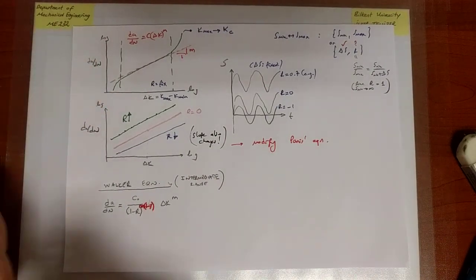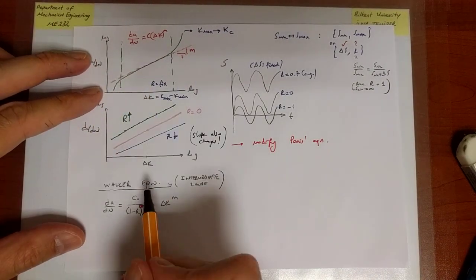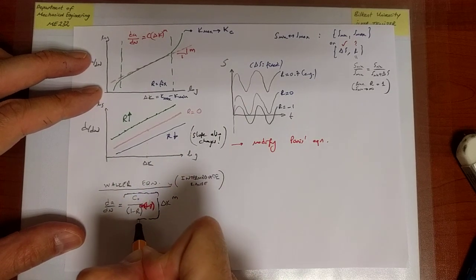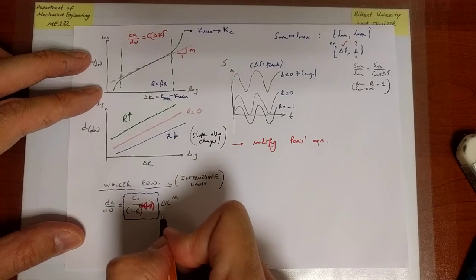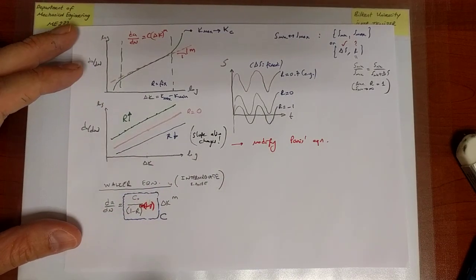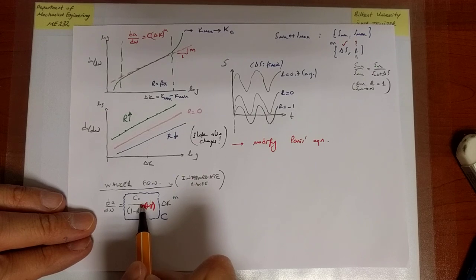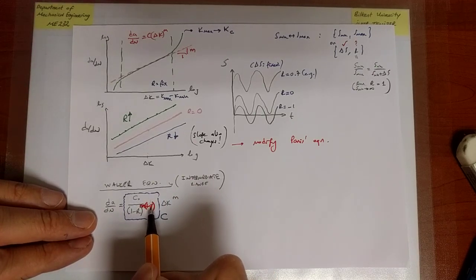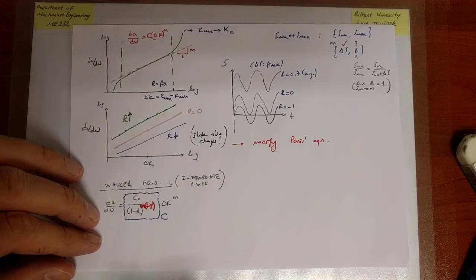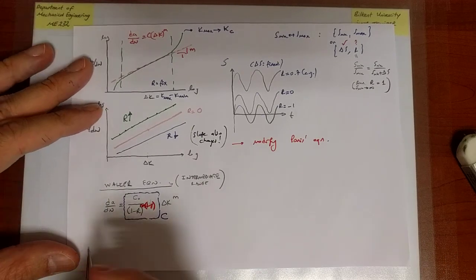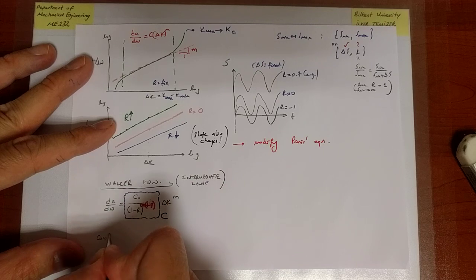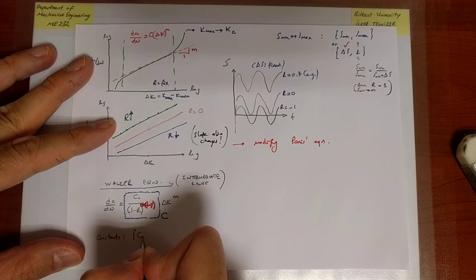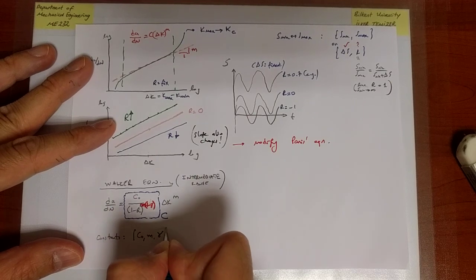So now, if you compare this with the Paris equation, what we're seeing here is that instead of a constant C in the Paris equation, we put a function which actually depends on R. M is the same material parameter. Gamma, on the other hand, is something that actually turns out partially load dependent. So the constants here that we need to know are C0, m, and gamma.